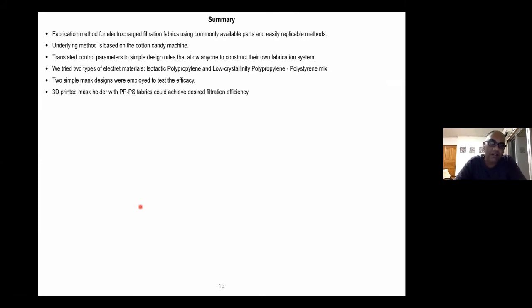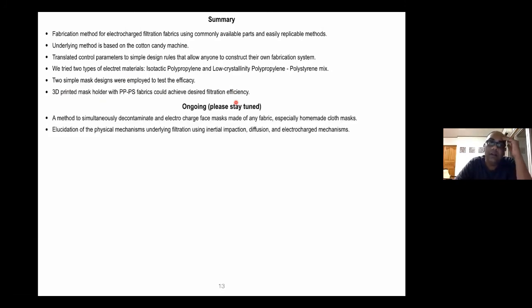So to summarize, I've tried to share a fabrication method for electrocharged filtration using common parts and easy methods. The basic idea comes from a cotton candy machine. We tried two types of materials, polypropylene or a polypropylene polystyrene mix, and two types of mask designs. We found that the 3D printed mask holder with polypropylene polystyrene could achieve the kind of filtration efficiency we expect for an N95 facepiece respirator. Ongoing work is a method to simultaneously decontaminate and electrocharge face masks made of any fabric, in particular homemade cloth masks.